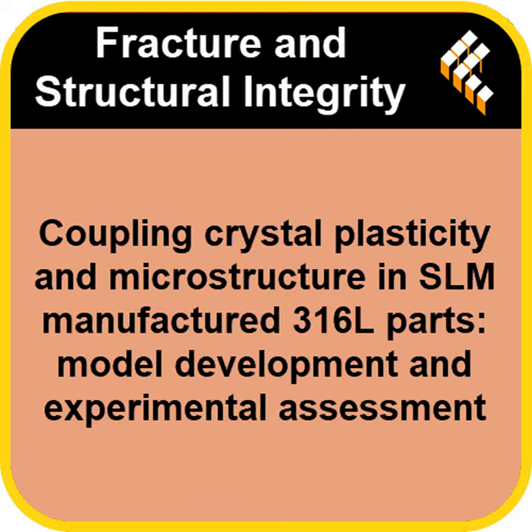What is the SLM process actually doing to this steel that makes it so different? Well, it begins with a bed of very fine 316L powder. The particles are between 20 and 53 microns. The laser melts and fuses this powder one thin layer at a time. The big advantage, like you said, is that geometric freedom. It's so much faster than traditional casting or forging for complex parts. But you're melting and cooling metal almost instantly. That has to create a pretty unusual microstructure. What did the analysis find inside these SLM samples?